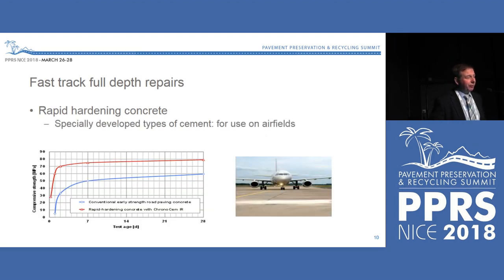When it has to go faster, for instance, on airfields, where sometimes there is only a very short window of 6 or 8 hours available to do the whole repair, then you need very special types of cement, no longer the traditional ones. You see here it's the conventional early strength concrete in blue, while you see the rapid hardening concrete, one of the different types which are available, where you see that the strength development goes much faster, and that in one day, or even, as I said, in 6 hours, you need to achieve the strength necessary to reopen for use.